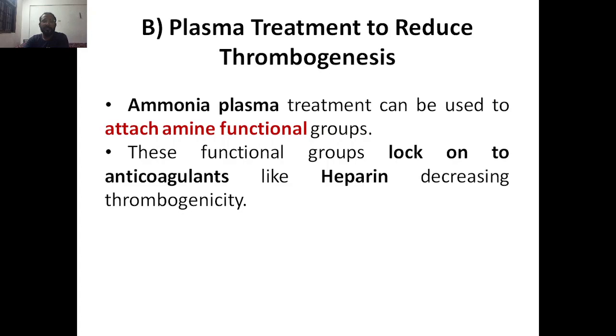Next, plasma treatment to reduce thrombogenesis. Thrombogenesis means clotting. When I am keeping some biomaterial inside my body, it should not cause thrombogenesis. So I need to reduce the thrombogenic property of that particular material. Ammonia plasma treatment can be used to attach amine functional groups. Here the amine functional groups will be attached on the surface so that they can reduce thrombogenesis. These functional groups lock onto anticoagulants like heparin, decreasing thrombogenicity, so that the clotting will not be there.